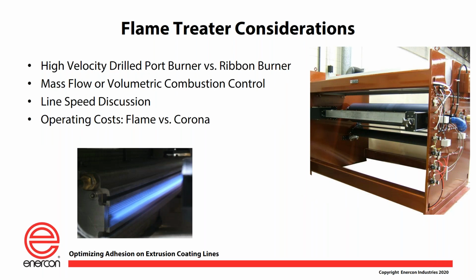Now, the flame treater, when you consider one, is designed with a high velocity drilled port or a ribbon burner. You can have it as a mass flow or volumetric control. The line speed is a big determination of whether you should use flame treating or not. Obviously, if your line isn't running as fast, running 200, 300, 400 feet per minute compared to 1,200, 1,500, 2,000 feet per minute, flame treating is probably not your application, because you've got an open flame and you could do some damage to your plastic film and your paper.